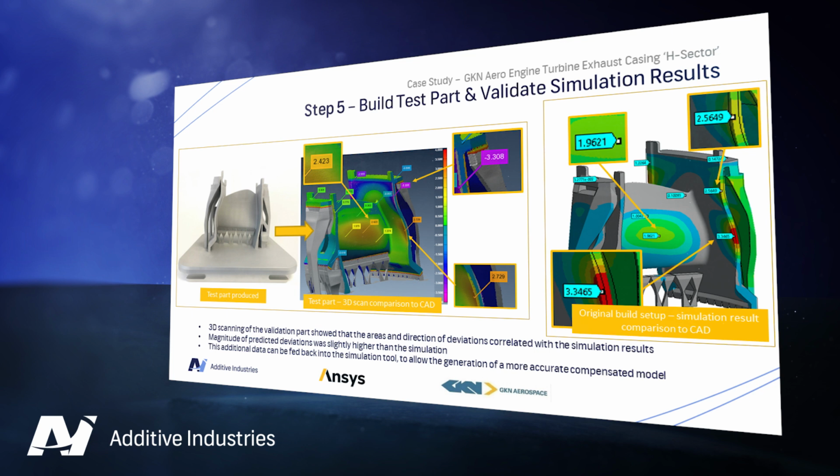The data shows there are a number of areas where the part was outside of the required surface profile tolerance. Most noticeably, around 3 mm on the flange and 2.5 mm on the vane. The results were shared with Ansys so that their software could be used to create a compensated geometry, which when printed should result in a part which meets the surface profile tolerance requirements.